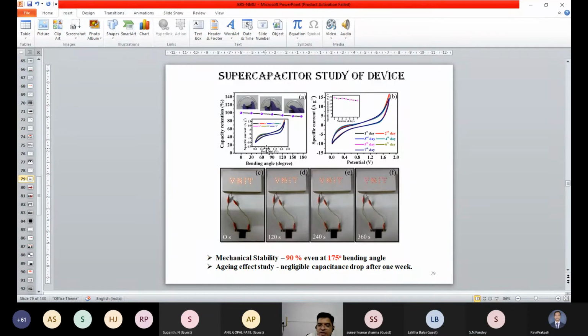So we have tested this mechanical stability at 175-degree bending angle. We have bent that device at different angles up to 175 degree, and we have tested the specific capacitance in terms of the capacitive retention, and we observed that it is 90% stable. So whatever flexible device we made is stable up to 175-degree bending angle. Not only this, we have tested that device for 7 days, completely continuous, and it is very, very stable up to 7 days, right?